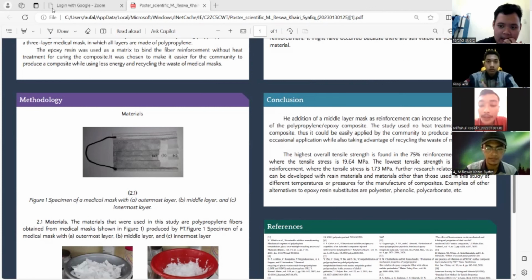75% reinforcement composition, where the tensile strength is 19.64 MPa. The lowest tensile strength is found at 25% reinforcement, where the tensile strength is 1.73 MPa.